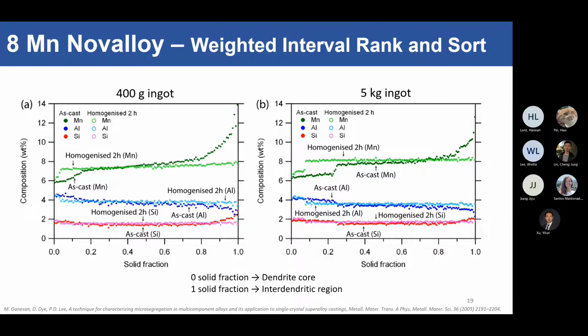You can see in both the small and the big ingots in the as-cast, the dark circles. So we look at this curve here. You can see that manganese segregates very strongly into the interdendritic region. Thankfully, aluminium and silicon don't segregate very much, so we only really need to pay attention to manganese.